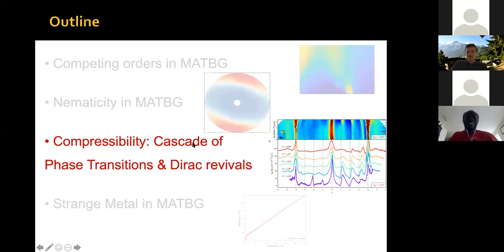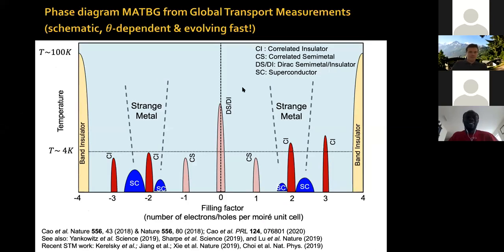So let me tell you now about our study of this cascade of phase transitions and Dirac revivals. So this is, again, a different version of the phase diagram that I showed you earlier. This is temperature here. This is filling factor, meaning number of electrons or holes per moiré unit cell. You have band insulators at 4 electrons or holes per moiré unit cell. At charge neutrality, you have a Dirac semi-metal, in some cases a Dirac insulator state. Some groups have reported an insulating state at charge neutrality. And then at each integer, you have either a correlated insulator or a correlated semi-metal state, depending on twist angle, parameters, and some conditions. And you have strange metal regions, superconducting domes, etc.